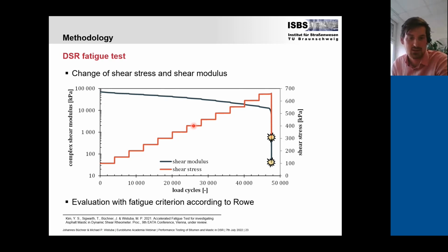So this is our proposed solution from this research project. From this stepwise increase of the shear stress, we can measure the shear modulus. You can see here it's quite linearly decreasing on a logarithmic scale, and then finally reaching a failure point after around 48,000 load cycles.